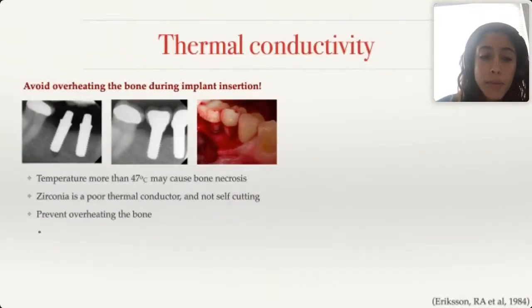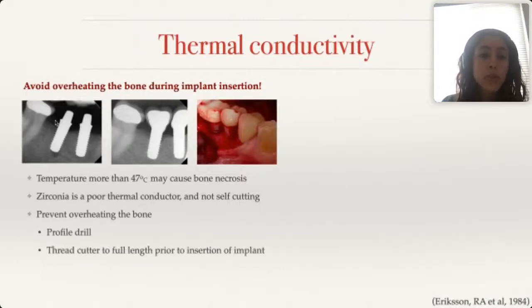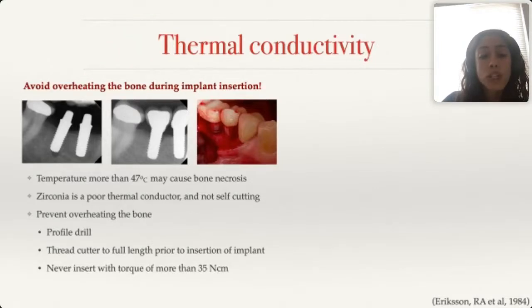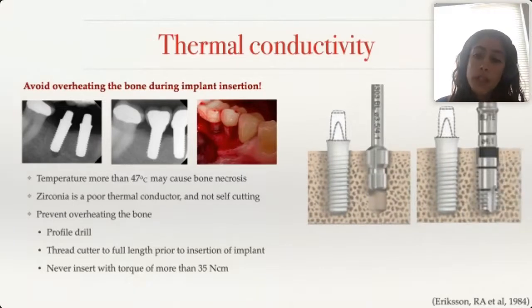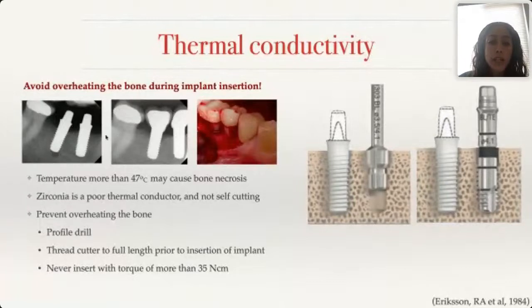So to prevent overheating the bone, we have to prepare the osteotomy well. We have to use the profile drill and the thread cutter, and we should never torque more than 35 Newton centimeters. Try not to exceed that, because more torque causes more heat, leading to bone loss around the implant and even implant failure. It's a very technique-sensitive placement for zirconia implants, because we need good primary stability, especially for one-piece implants with the abutment exposed, but we also don't want too much torque causing overheating. It takes a lot of care compared to placing titanium implants.